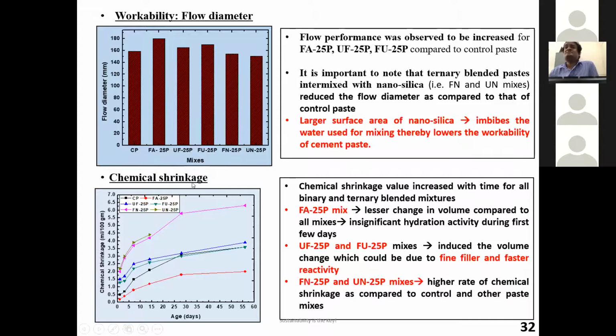Now we go to the chemical shrinkage. Chemical shrinkage is a separate method. There is a method, as I told you, which is measured through the flask. Now you can see here the mix in which I have ultrafine particles and nanoparticles, the blended mix, the UN25. You can see here, after 14 days, there is no more data. 28 days, 56 days data is not there. Means there is some problem.